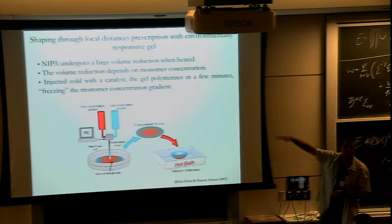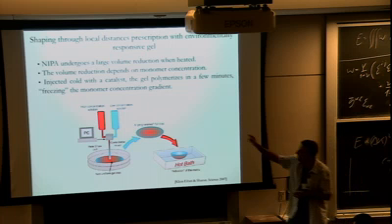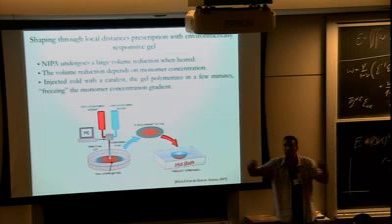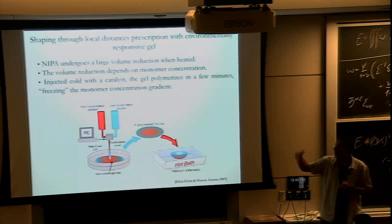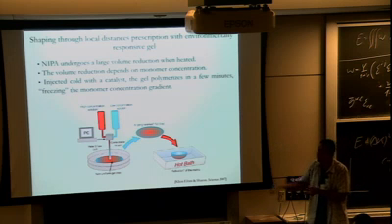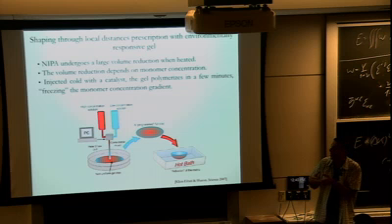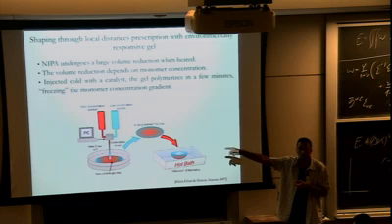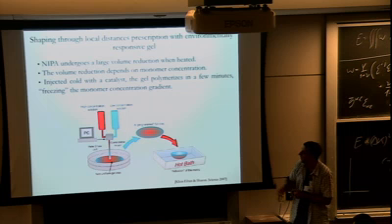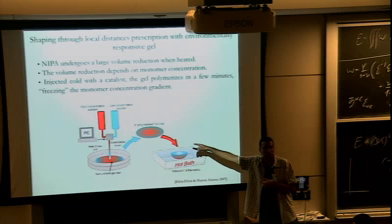Nothing varies across the thickness of this thing. But between the center of this thing and the boundary, I inserted some structural gradient in this gel concentration. It's environmentally responsive, meaning that when I heat it up, it's going to shrink. And its shrinking ratio depends on if it's dilute or dense. In the densest regions, it's going to shrink very little.